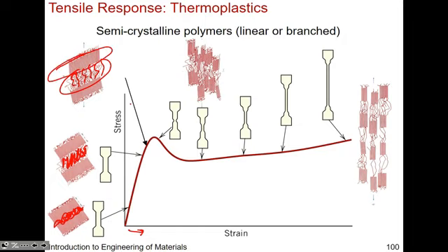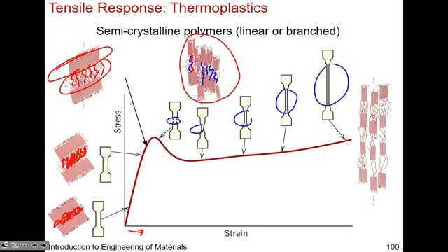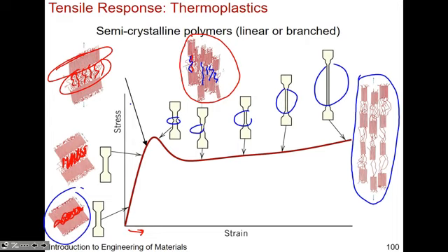They're already lined up. And then as you go beyond the point of elastic deformation, now your material is deforming in a way where the crystalline chains are also coming apart and your amorphous regions are becoming even more elongated. And you could see that here in the cross-sectional areas as well. You could see it being elongated. And finally, near fracture, you are basically now starting to pull apart the carbon-carbon bond. So here you were just changing the secondary type bonding, but at fracture, you're basically just ripping apart the primary carbon-carbon bond. You are just breaking apart your material. Your secondary bonding has been long gone.